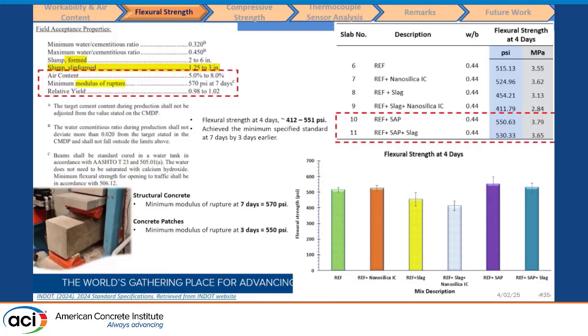And then for flexural strength, the beams were tested at 4 days. We are looking at how early we can open this pavement to traffic. So we tested at 4 days, and these are some of the results we obtained. The range of results was between 400 psi and 550 psi for flexural strength at 4 days.